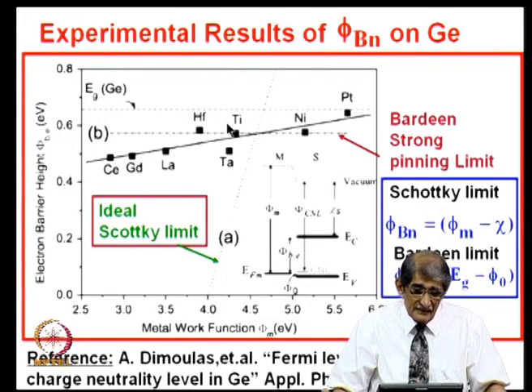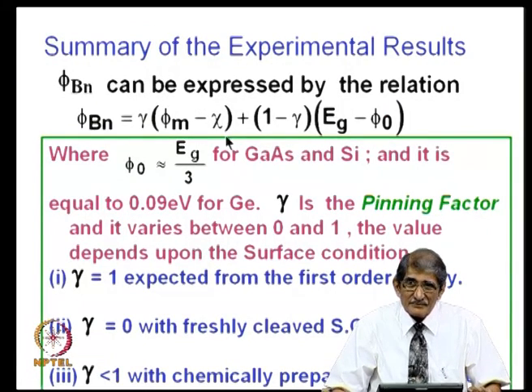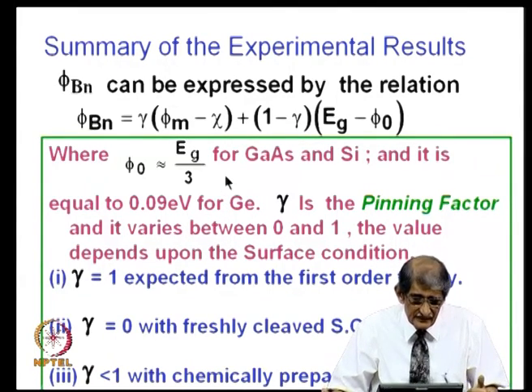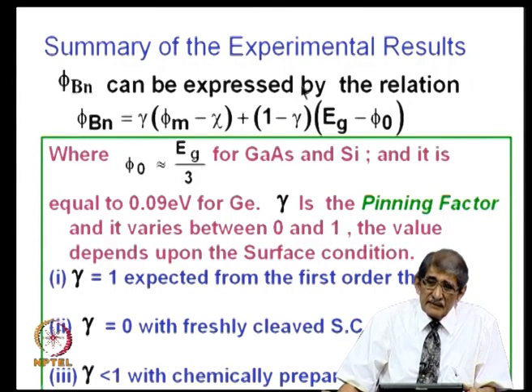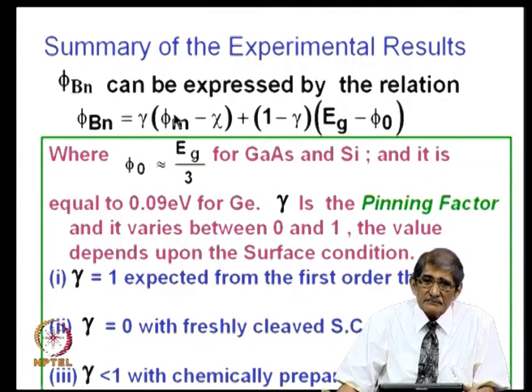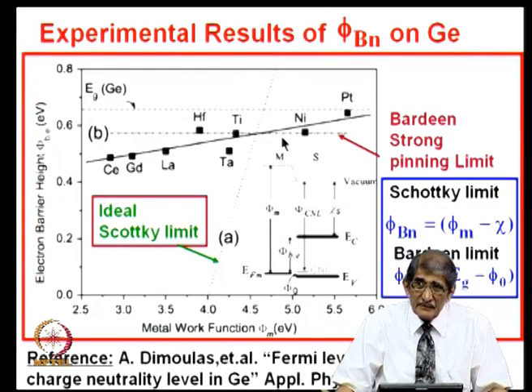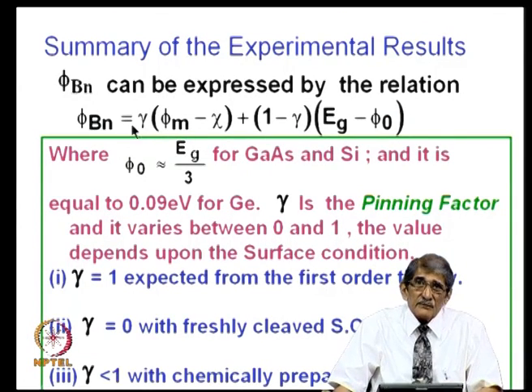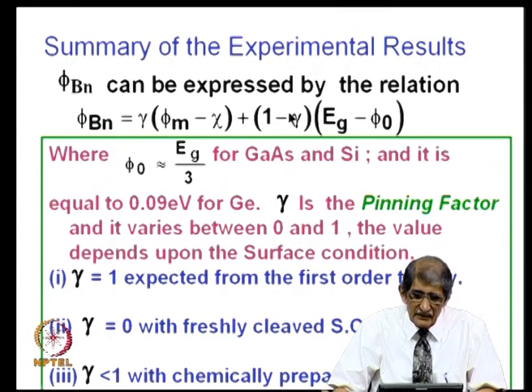So, from these things one can fit in a graph like this. I will just discuss this. How this comes up and what are the implications of that, more details we will take up in my next presentation. So, what we have concluded from these experimental results is, phi bn can be expressed by a relation, ideal case it is phi m minus chi. In practice, I can express phi bn as gamma times (phi m minus chi) plus (1 minus gamma) times (Eg minus phi naught), because you saw that it depends upon Eg minus phi naught. Okay. So, gamma equal to 1, second term is 0. Gamma equal to 1, phi m minus chi, that is the ideal case, first order theory.